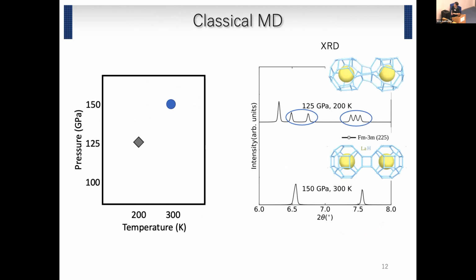Okay, so let us start with the result of classical MD. In this calculation, quantum effect is not included, just the finite temperature effect. Here I'm showing two representative results. At 200 Kelvin and 125 gigapascal, the pressure is low and the temperature is low. In this case, if we calculate the X-ray diffraction pattern, then the cage is distorted and we see many subpeaks. But when the temperature becomes high and the pressure becomes high, the structure becomes symmetric and the subpeaks disappear.